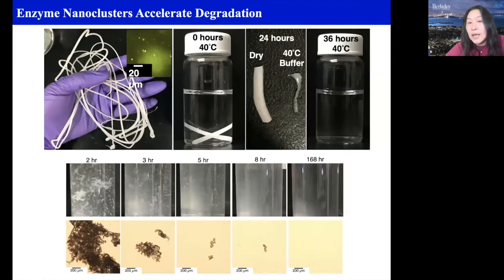into a wire. And then subsequently, you can see the wire can be degraded. This happens to be a piece of plastic sheet that we just put into a buffer and monitored to see it disappearing over time. What is important for us in this case is really those microplastics. We take them out and study them under the optical microscope to see how the microplastic degrades. And you can see that under the optical microscope, the plastic is forming this porous network.